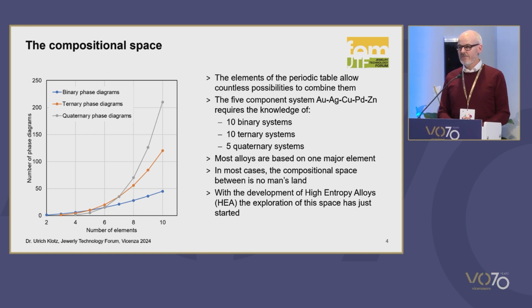We see that we already have to know 10 binary systems, 10 ternary systems, and 5 quaternary systems. So this is a huge space, and we don't know this space. We only know the regions around one corner, let's say the gold-rich corner, the silver-rich corner, the copper-rich corner, the palladium-rich corner, but you're aware that a gold alloy is very different from a copper alloy and from a palladium alloy. So actually, we know very little about the space in between. And so it's actually a no man's land that